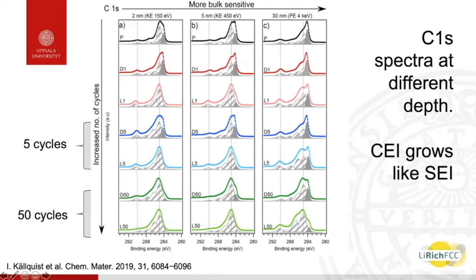And if you look at the carbon spectra, what kind of cathode electrolyte interface, because this is a cathode, and we are used to having rather thin cathode interfaces, like I showed for the lithium iron phosphate case. Here after 5 cycles and 50 cycles, we can see a lot of organic reactions on the surface, and it's actually growing thicker and thicker. It seems like instead of a cathode electrolyte interface, we have more of an SEI, actually, like an anode.